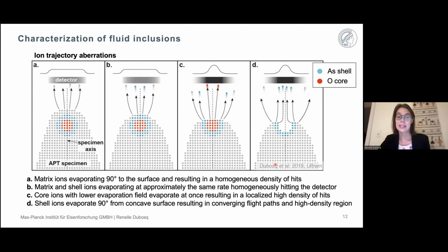Then in image D here, once we've evaporated all of the ions from the core, we are left with shell ions, and they evaporate at 90 degrees from the concave surface here, which results in their converging flight paths and also leads to a high density of hits on the detector. So this leads to these features appearing as high point density features and spherical clusters in the 3D reconstruction.